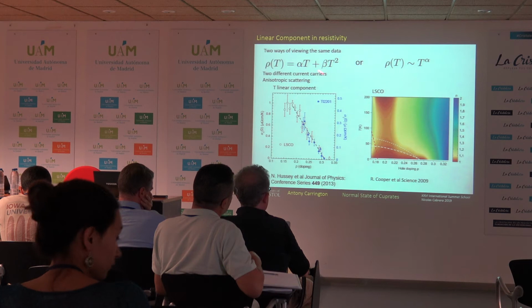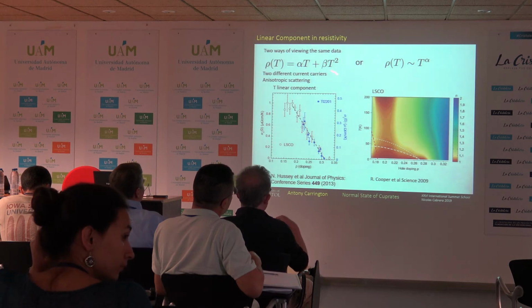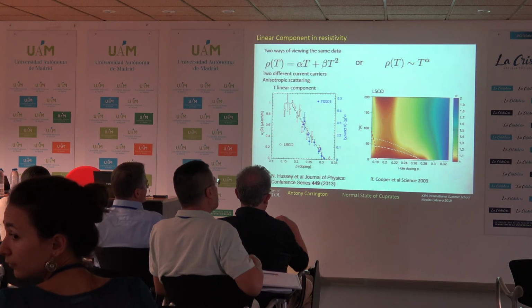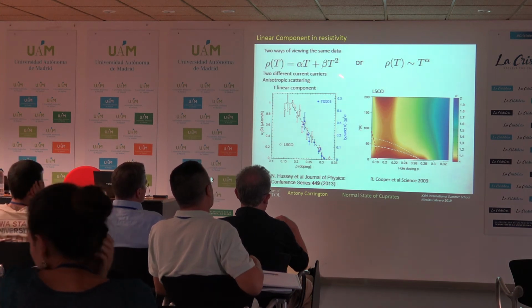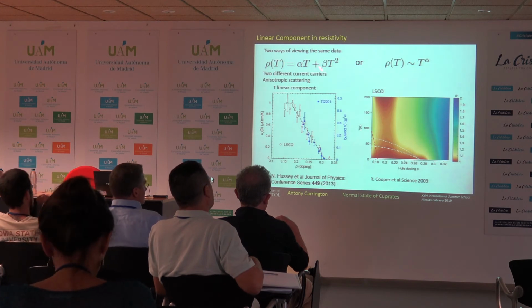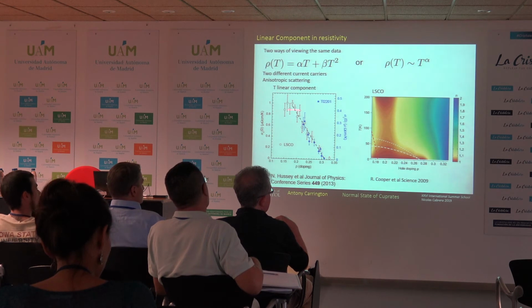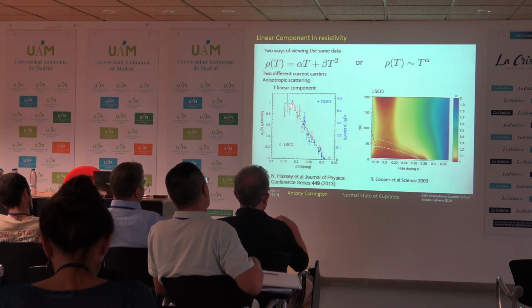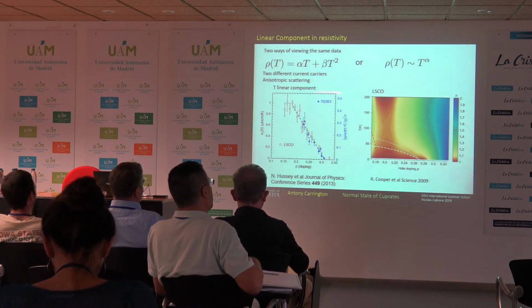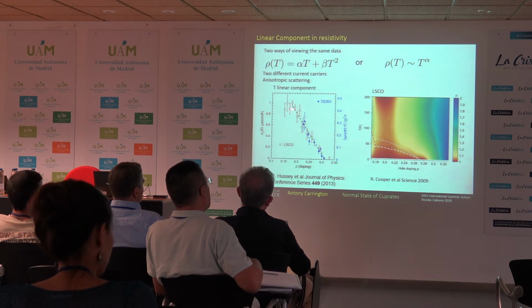But if you go to a region where you're supposed to have T-square behavior, the question is if you go to higher temperature, whether you recover exactly the same linear behavior as it had before. So I haven't shown this, but what's found is that this beta coefficient doesn't change very much as a function of Tc. So as you get to this point here, then effectively it's all linear in T. Okay, so this coefficient doesn't change, and this one does.